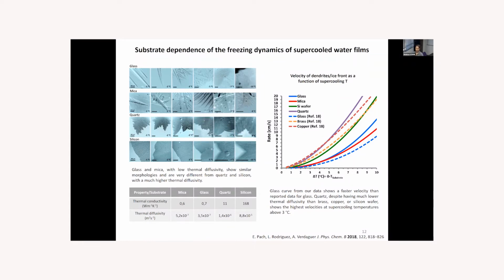And these are much different from quartz and silicon with much higher thermal diffusivity. We have plotted the velocity of the dendrites and the ice front formed in the first stage of the freezing as a function of supercooling temperature. And we could see that the glass curve from our data, which is in blue here, shows faster velocity than that reported for the glass in literature. Quartz, despite having much lower thermal diffusivity than brass, copper, or silicon wafer, shows the highest velocities at supercooling temperatures just above 3 degrees Celsius.